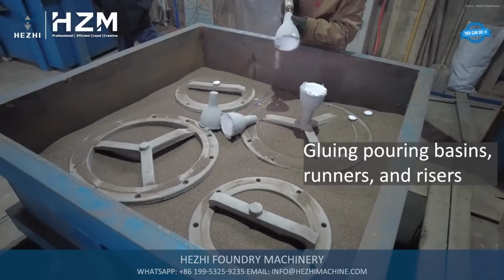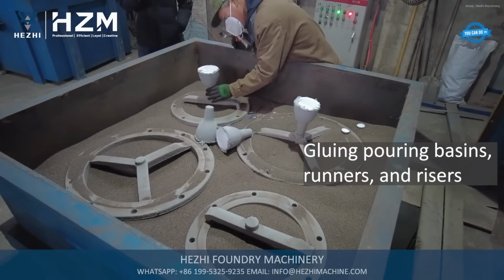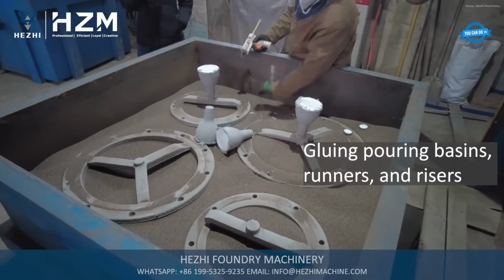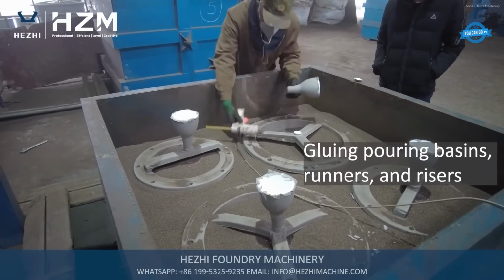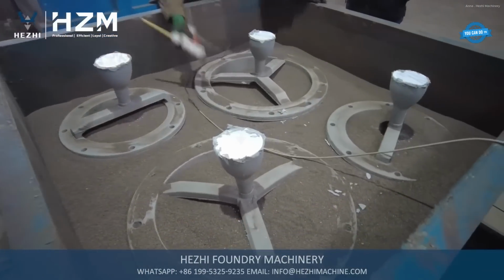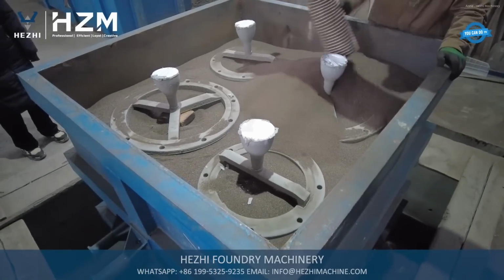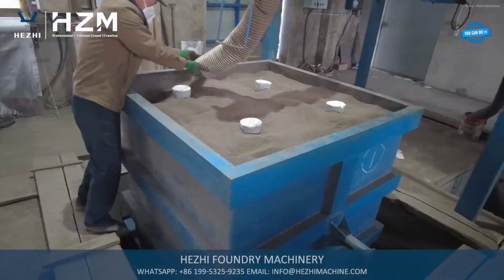final steel tubes. These foam patterns are then coated with a refractory ceramic slurry to provide a durable surface for molding. After drying, the coated patterns are placed in an oven room for controlled heating, ensuring structural integrity during the casting process.